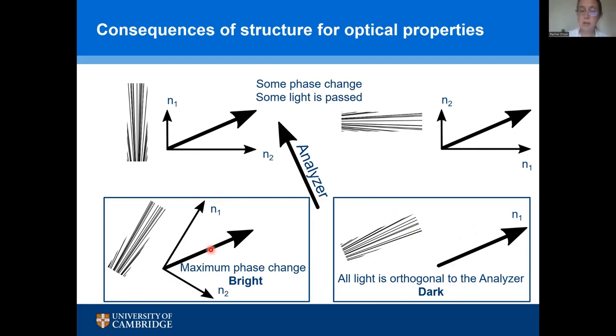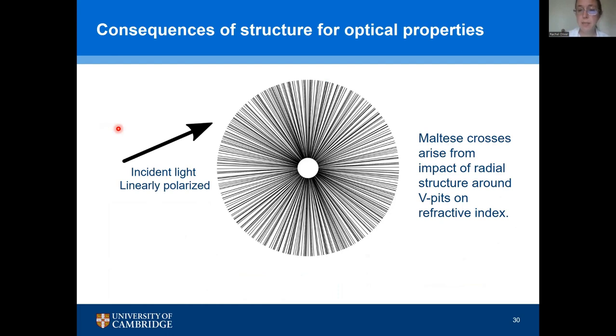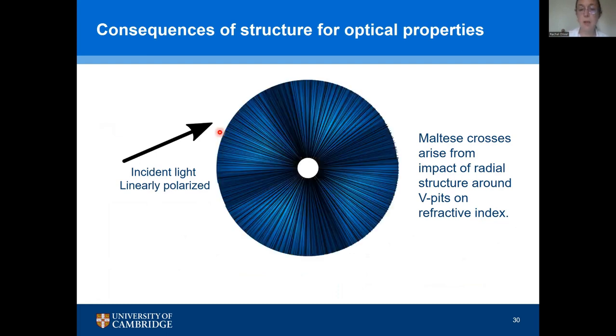And at angles which are a bit closer to the light being parallel to the pores, we'll see a little bit of phase change and some light passing through, but not very much. So that means if we then think about what we expect to see, we'll have regions where the light is either perfectly parallel to the pores or perfectly perpendicular to the pores, where we're only sampling one of the two refractive indices, where the material appears dark. And then as we get closer and closer to the point where we have that maximum phase change, the whole thing will appear the brightest. And that gives us this Maltese cross appearance from this radial structure that we accidentally created.